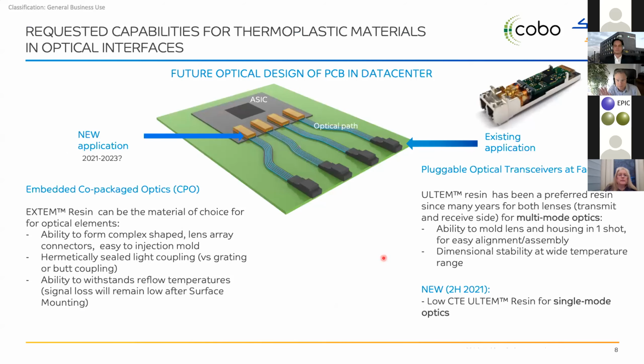All right, so now a completely different application, and well, Jose knows more about this than I. But if you talk about the PCB in a data center, everything in a data center is already with light fibers, but the final part, the PCB, is still with copper. And the copper has issues when you go above 100 gigabit per second. So with increased bandwidth, in the future we have to go there. Then you have to make the copper thicker and thicker, and there will be electrons jumping from one trace to another trace. So to avoid this crosstalk, there's only one solution, and that is to go fully optical, which means that the whole PCB will be covered with waveguides.